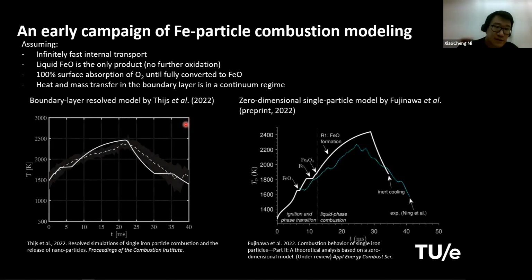So this is what we got. These are two independently developed models. On the left is work developed by my colleague Leon Theis and his colleagues. He used a boundary layer resolved model, basically a 2D axisymmetric model. You resolve the gas boundary layer around the particle. It's not a single 0D particle model. And he showed that his result, this solid line, matches Ning's experimental result, the laser ignited cold environment result, pretty well. Overall, the trend is pretty close, and the peak temperatures also agree well with each other.